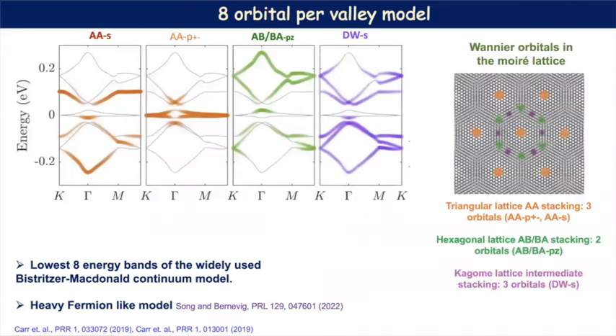So here I'm showing the Wannier orbitals on the Moiré superlattice. There are different orbitals. There are 3 orbitals which are on this triangular lattice, formed by the AA stacking regions. And there are 2 orbitals in the AB and BA stacking regions, which form this hexagonal lattice. And we also have 3 orbitals in the region where the stacking is intermediate. And you can see here how these orbitals form these different 8 bands, which are color coded here.